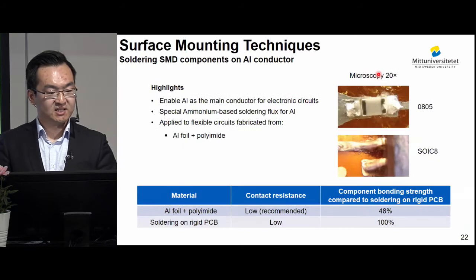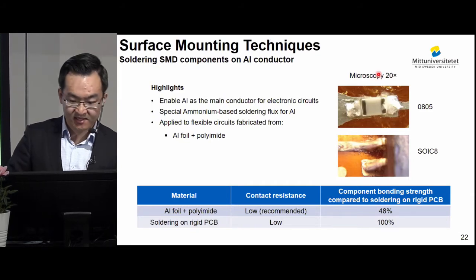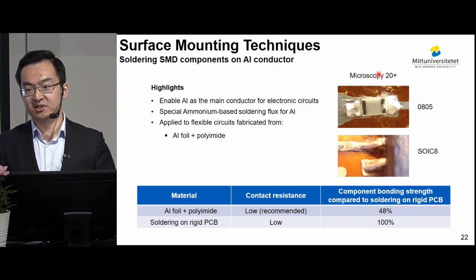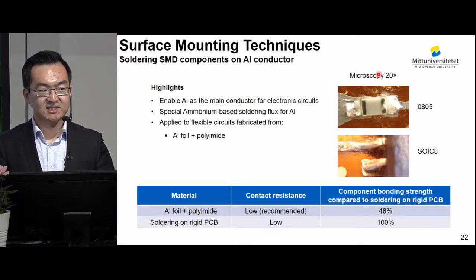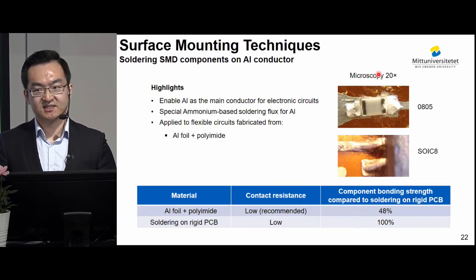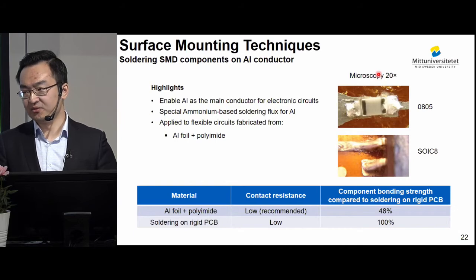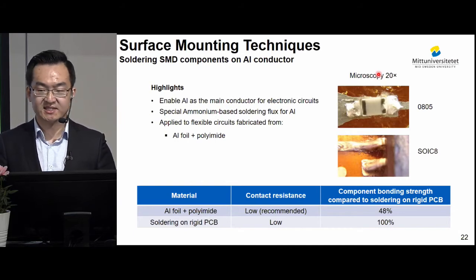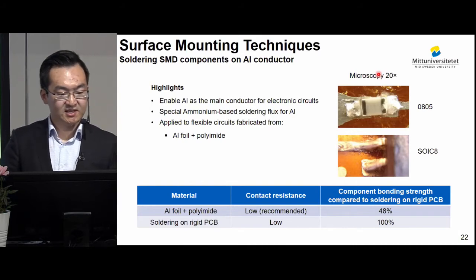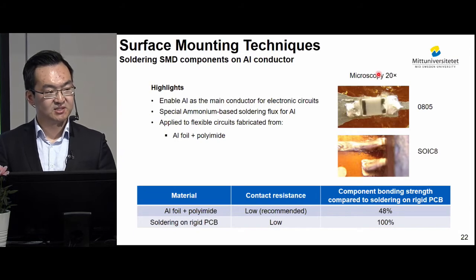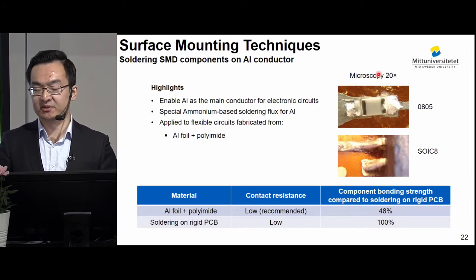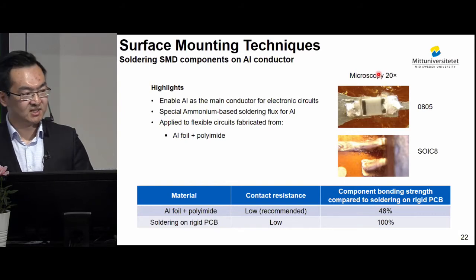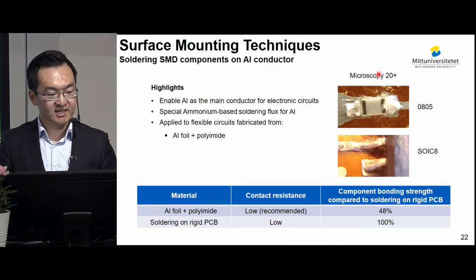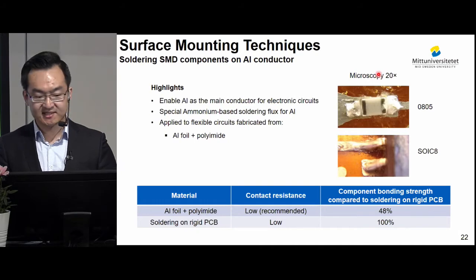The fourth surface mounting technique is that we developed a method to solder components on aluminum conductor. As we all know, it is very difficult to solder components on aluminum conductor because aluminum has a very dense surface oxidized layer that grows almost immediately. And it's very thick and dense, so the solder flux used for copper conductors is not aggressive enough to remove this oxidized layer. So in this thesis, we developed a method to use a special ammonium-based soldering flux to solder components on aluminum conductor. And by doing so, we could enable aluminum as the main conductor material for electronic circuits.